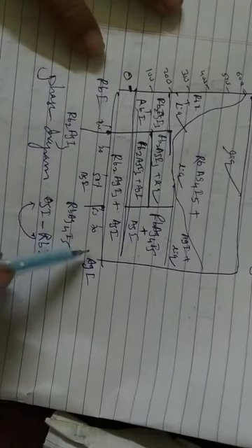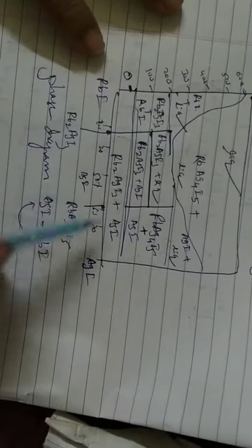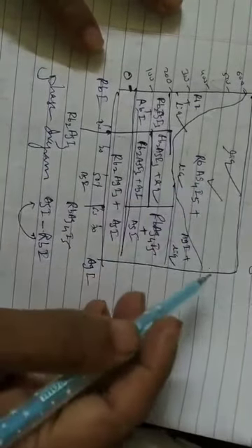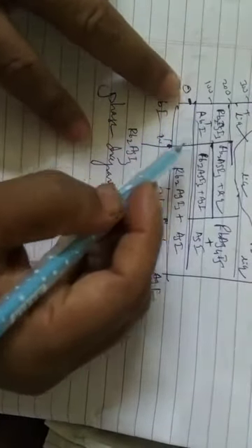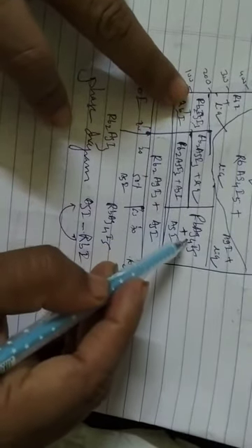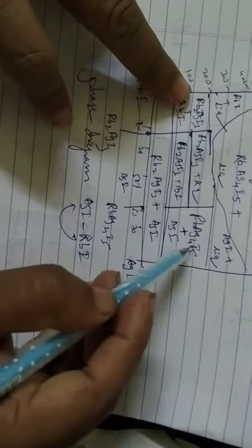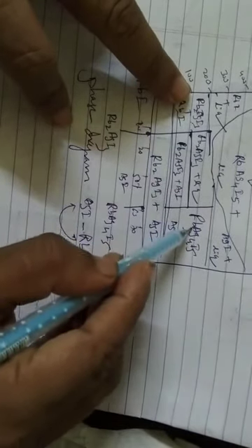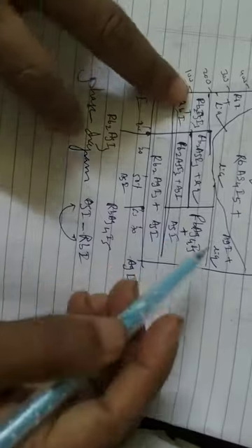And this is the phase diagram here for AgI and RbI combination, where we can get this composition which is having the highest conduction value at room temperature compared to the alpha AgI. Now if you consider this phase diagram, two binary compounds exist here: Rb2AgI3, this is one binary compound, and here RbAg4I5. So these two binary compounds exist here.